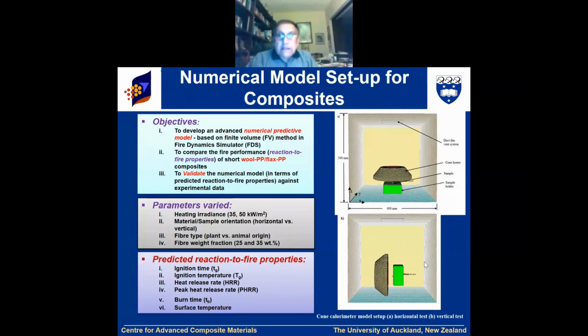So we have, and this is the thing I said, vertical. So vertical burning is done for aerospace. So we also analyze for horizontal, vertical, and also we published a paper where this can be at any angle, because fire will not follow this angle, 0 or 90. So at any angle, we try to predict what sort of fire performance or fire characteristics will be seen. So we predicted ignition time, ignition heat release rate, peak heat release rate, all those things.